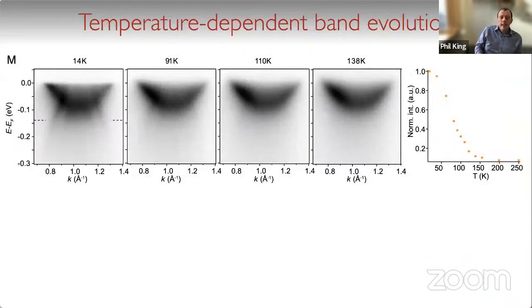Okay, and if we take these titanium telluride monolayers, we can look at the temperature-dependent evolution of the electronic structure. You can see here that as we do that, these backfolded states in the valence band really disappear as we increase the temperature. This is another signature that this backfolding is due to a charge density wave instability, and the spectral weight falls off and is basically vanished by, I don't know, 120 Kelvin or so. So below that temperature, we think we have a charge density wave in the system.